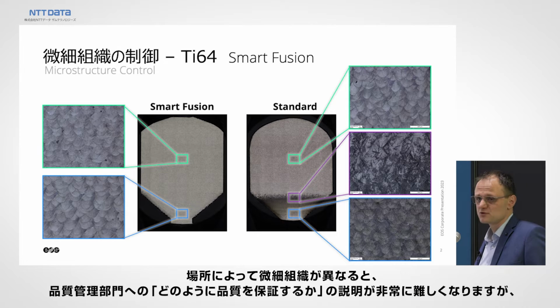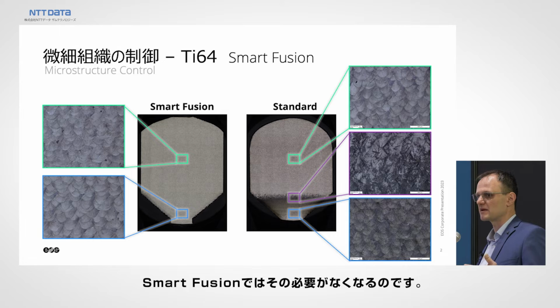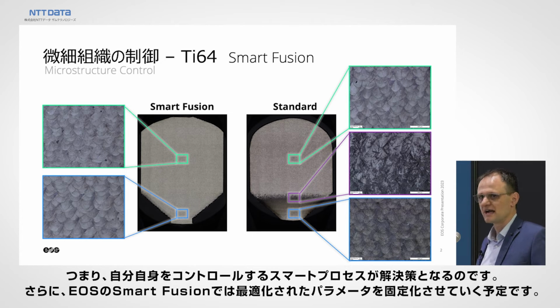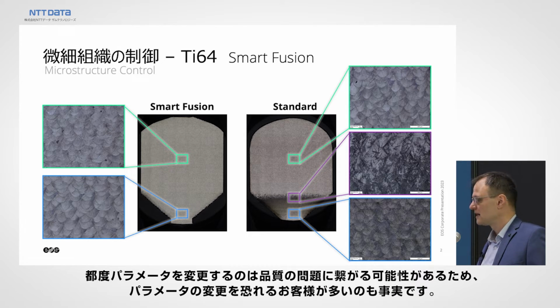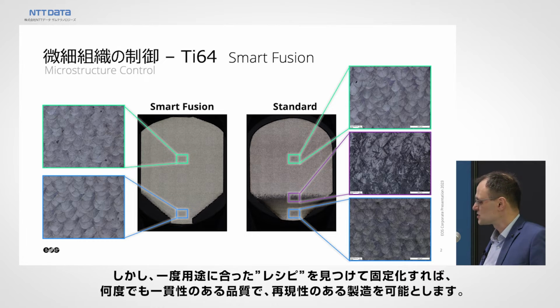So it's difficult. So with Smart Fusion, we don't have these problems at all. So there is no segmentation in various areas where you have different microstructures and you have to tell your quality department how am I going to qualify for that. So the idea of having a smart process that controls itself is the way forward. And EOS in Smart Fusion also has the possibility to freeze those parameters. So a lot of customers are always scared, for good reason, that changing the parameters all the time can lead to quality problems. But once you have found the right recipe for your application, you can make a lock behind that and you can just rerun that component over and over again to have the same repeatable part quality and consistency.